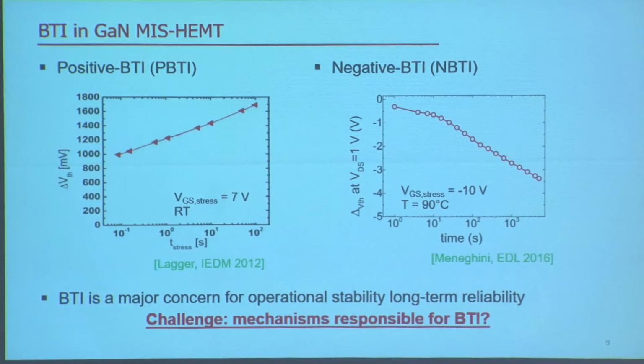BTI has been observed in gallium nitride MIS-HEMT. Both PBTI and NBTI have been reported. On your left side, you see a recent work, a paper published in IEDM, where the authors observed a large positive VT shift when they applied a 7 volt gate stress at room temperature. On the right-hand side is a work reporting negative bias temperature instability, where the authors observe a large negative VT shift when they apply -10 volts at 90 degrees C. The magnitude of the delta VT shift is quite large for MIS-HEMT, and in comparison with silicon devices, it's much larger. So it's a major concern that we need to address for gallium nitride MIS-HEMT. But it's very challenging because the physical mechanism behind the BTI is not very well understood.